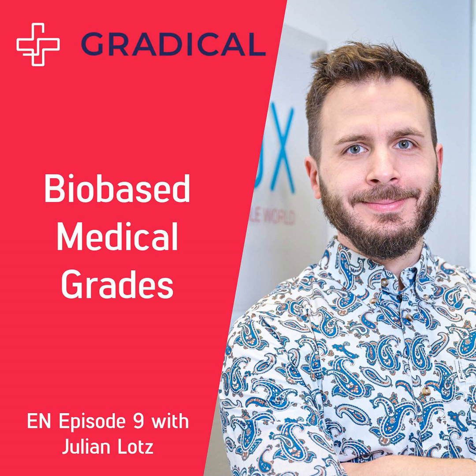I mean, you have the advantage that PLA doesn't degrade too fast. Yep. You have to have a look at the degradation rates. For example, if you look at biopolymers like PBS or PHAs, depending on stabilization, they significantly change over time, also in, let's say, standard storing conditions. And there, the material getting brittle and losing strength is an issue. That's why we don't really use them so far.